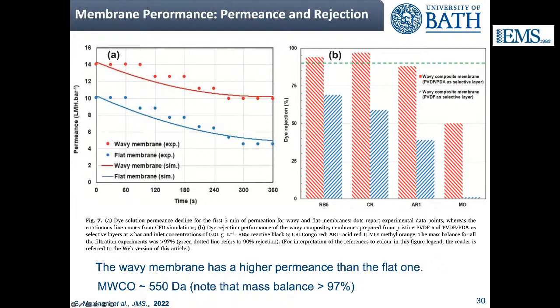And I would like to highlight that because we are using dyes, and there's always the risk of having adsorption rather than rejection, we did mass balances in all our tests. The mass balance is always more than 97%. So this is actually rejection data and not adsorption data, as you find in many publications that use dyes to see the performance of the membrane, but instead are actually doing adsorption of the dyes on the membrane.